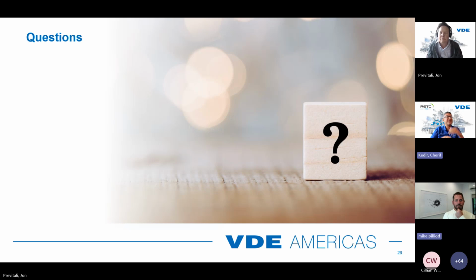It takes longer, but you can figure out which one broke it, because you figure out where it actually broke. In pictures of a hailstorm going through a solar farm, you get a checkerboard pattern. You get one module next to another, and this one's pristine, and this one has 50 different breaks on it. It's not that the one that broke got 50 rate limiting flaws on it. Glass breaks from pre-existing flaws. So if one hail ball hits and breaks the glass, any subsequent hail is going to cause more failures, because you already have a crack in the glass on the front side.